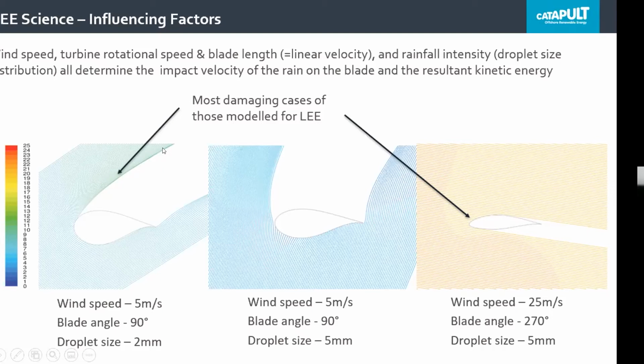on the leading edge of the turbine. But under the same conditions of a wind speed of 5 meters per second, same blade angle, but a droplet size of 5 millimeters, which you would expect to be more damaging, you actually see that the 5 millimeter droplet doesn't impact the leading edge at all because of the airflow. And the most critical of the cases that we modeled, with a 25 meters per second wind speed, a blade angle of 270 degrees and a droplet size of 5 millimeters, causes the most extreme damaging case in terms of impact energy.